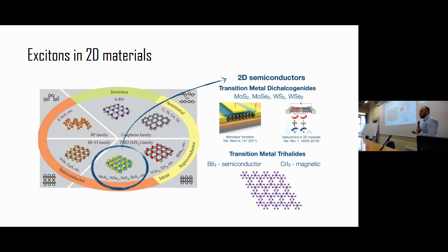They have a particularity, and it is that the lattice, so the stoichiometry is, for example, bismuth iodine 3, because you have a missing atom in the lattice. So the new thing of this material is that because you have this kind of hole, the dielectric screening is reduced a lot in comparison with, let's say, a normal 2D semiconductor that already has a very small screening, no?